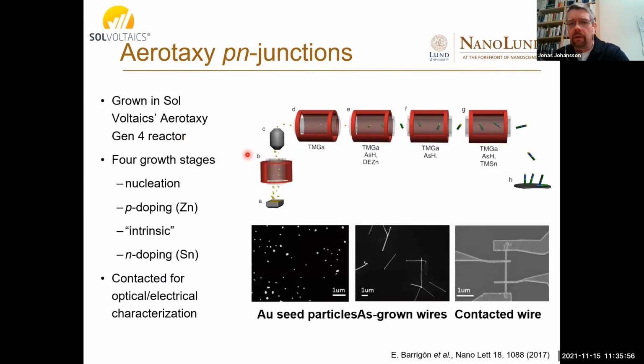One to two seconds, maybe more, in the order of seconds is the residence time, and it grows about 1 micrometer per second. Very, very fast growth. Still crystalline. It's quite fascinating that it grows so fast. Okay, thank you.